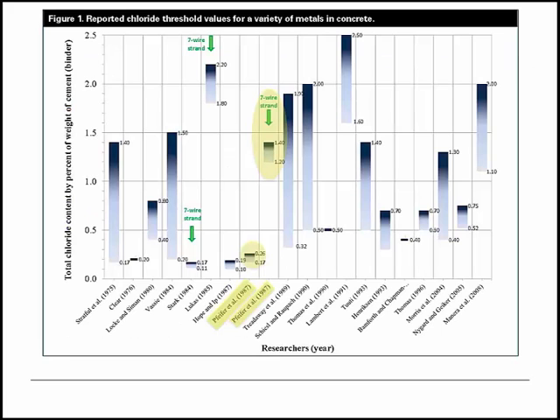So this is a graph that was put together by the Federal Highway, plotting out the chloride content thresholds that have been reported by researchers since 1975. And the two highlighted numbers are the work that I mentioned done by WJE in 1987, Don Pfeiffer and others, with the little bubble on the left representing reinforcing steel in concrete, where the chloride content threshold was found to be 0.17 to 0.26, and the larger bubble on the right being strand in concrete, where, as I noted, the chloride content threshold was as high as 1.2 to 1.4.